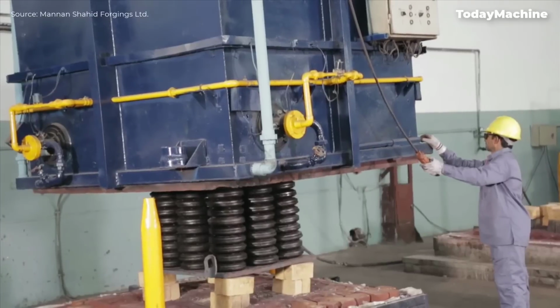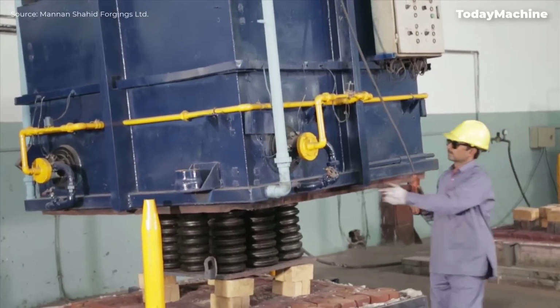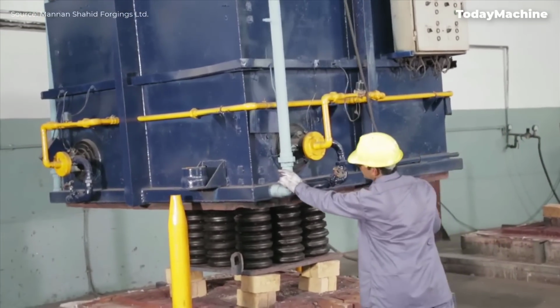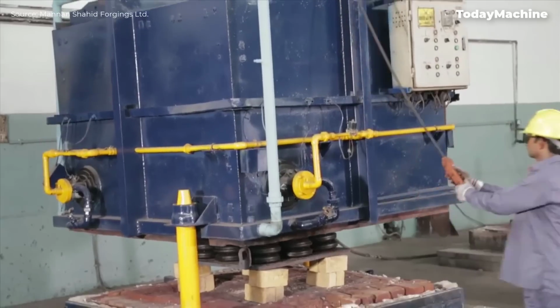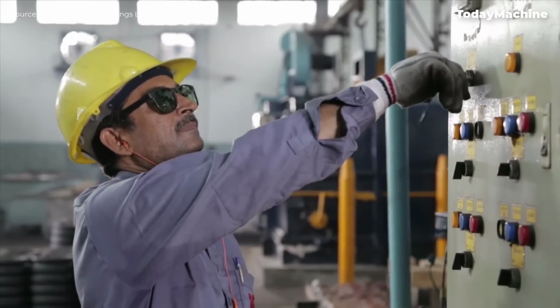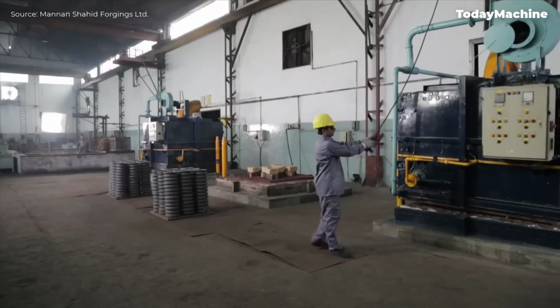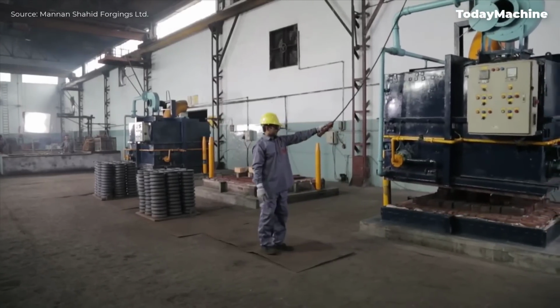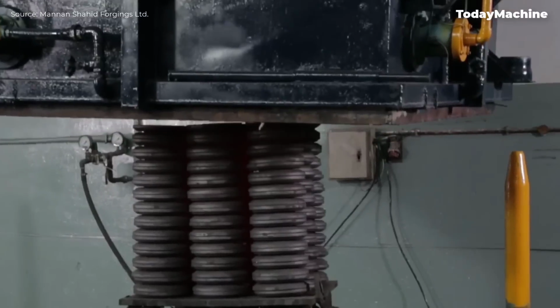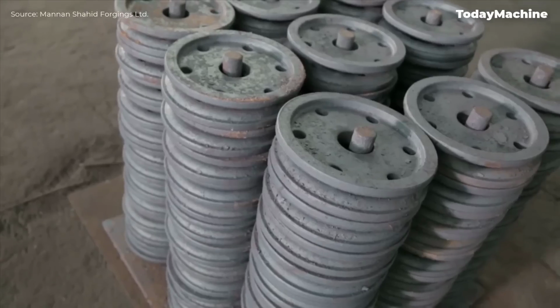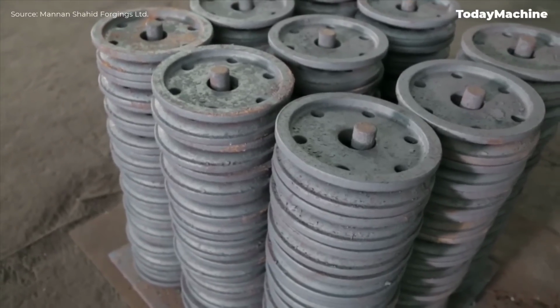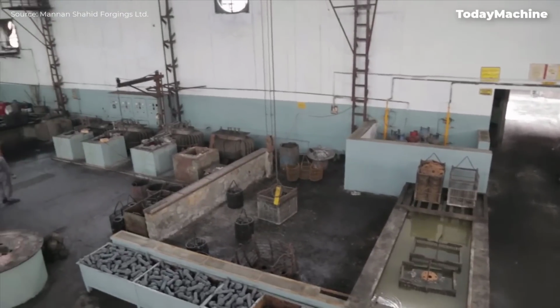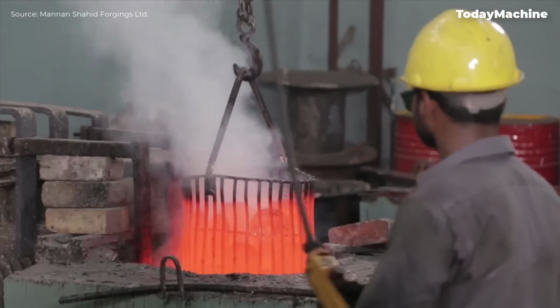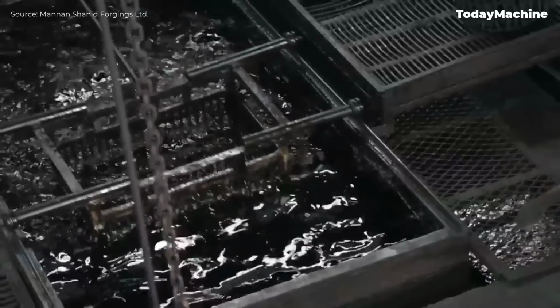After forging, the components are subjected to a series of heat treatments, including normalization or isothermal annealing, in modern gas-fired top-hat furnaces with a 1-ton capacity. The accuracy of these furnaces ensures minimal variation in the machining process, resulting in consistent quality. Hardening and tempering are carried out in electric salt bath furnaces, with temperature accuracy maintained within 5 degrees Celsius.